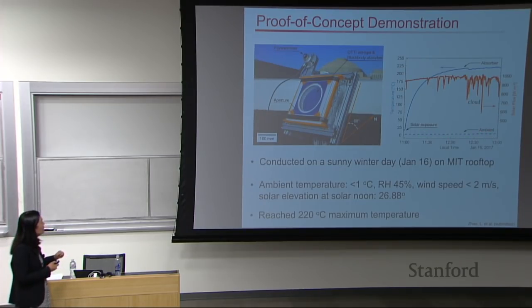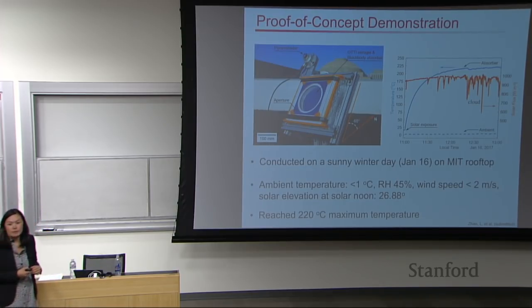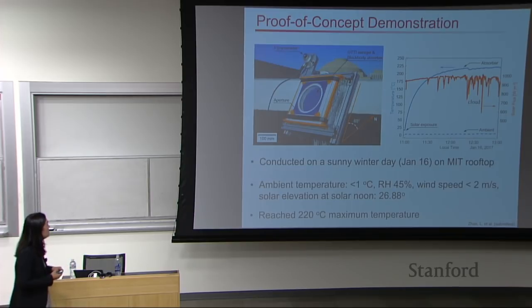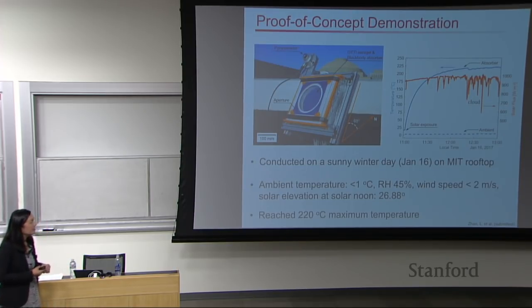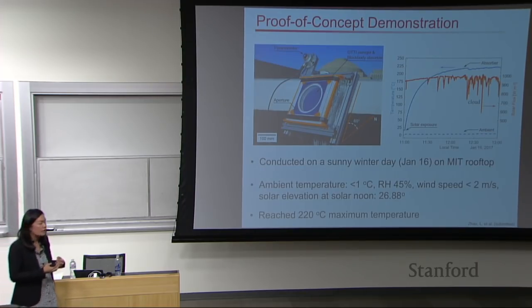And so from this prototype that we've now faced towards the sun, you can see that, in fact, here again the temperature is in blue. Here's the solar flux measured, and here's the ambient, right? So you can see that upon solar exposure, you can reach over about 200 degrees Celsius, right, about even that of 220 degrees maximum temperature. And so this suggests that there is significant promise in finally being able to tailor these nanostructured materials, in this case these aerogels, in a way to help us achieve really